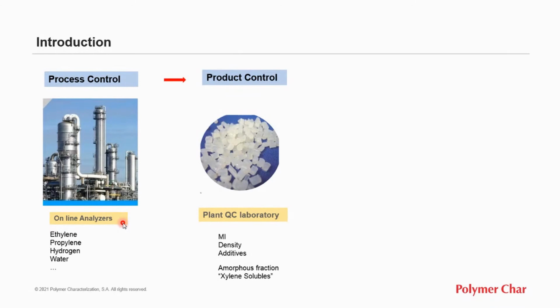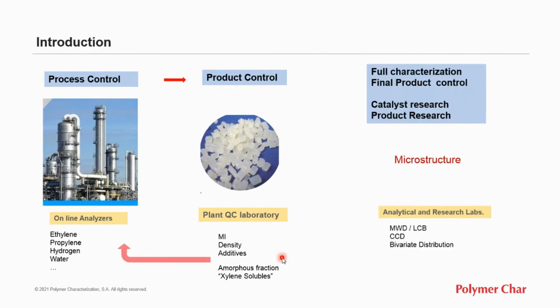Then in the plant QC laboratory, the product itself is controlled by measuring some properties such as melt index, density, additives, and also the solubles in the case of polypropylene, and that information can be fed back and used for process control. We know that those properties, melt index and density, are in fact related to microstructure. Microstructure means molar mass distribution as well as chemical composition distribution, as we have seen.